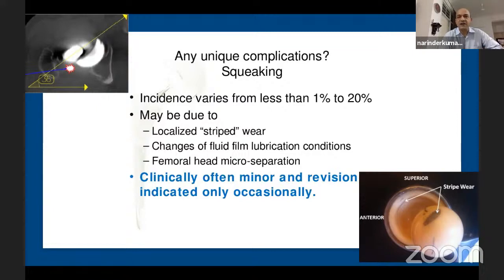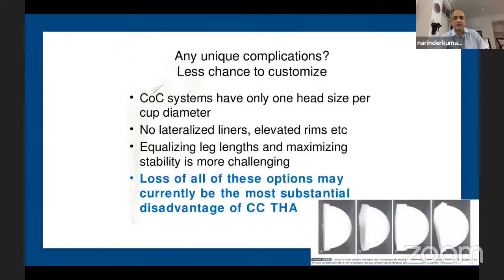Hard-on-hard bearings are very high-demand surgeries. All the principles which were outlined in the planning of the surgery and in the cemented and uncemented components, which were highlighted by the previous speakers in sessions 1, 2, and 3, need to be followed very meticulously to have a perfect position of the acetabular component, as well as a good offset from the femoral side also, to avoid any stripe wear which will lead to squeaking of the hips, because that changes a lot of biomechanical conditions there. But then clinically, these have now become fairly rare because we understand it much, much better.